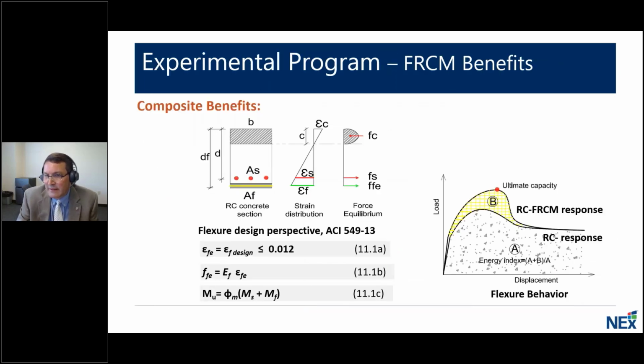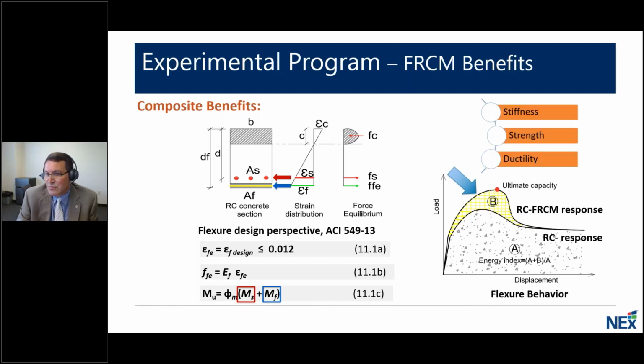The mechanics involved includes the contribution of the steel and that of the FRCM repair system. The repair system not only adds additional flexural capacity from the steel or the existing strengthening system, of course, but it also adds the additional capacity of the external repair system. It may be noted that additional displacement ductility or energy to the system is represented, as you can see here, as area B. And so our work really examined the stiffness, strength, and ductility of these repair systems.